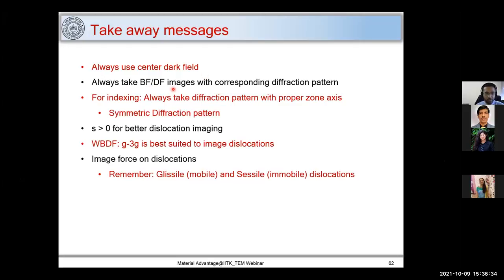Always take bright field and dark field images with their corresponding diffraction pattern. So from now onwards, when you are taking any TEM images, always do diffraction. That is very important. Next, for indexing, always take the diffraction pattern with the proper zone axis. This makes your life much easier. Tilt your sample to get to the proper zone axis and take a diffraction pattern from there. That diffraction pattern will be symmetric and very easy to index. You don't have to depend on anyone for indexing such diffraction patterns.